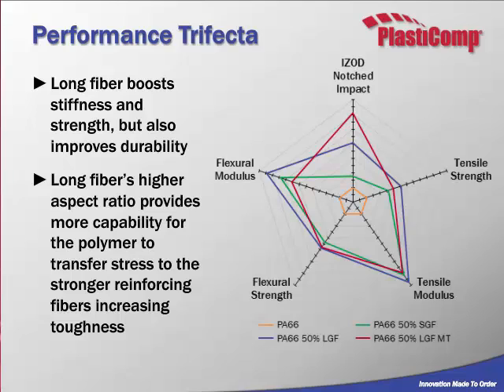Now this slide just shows a spider diagram of several materials that are compared to each other. In the center is the unfilled product, and you can see the properties there are quite low in comparison to even the short glass product, which is labeled as SGF. And then we have two products that we're highlighting here. The first is our standard long glass fiber product, and then we also have what's called a maximum toughness grade, which is the MT product. Where that really stands out is in its impact performance, and we'll touch on that a little bit later in the presentation. But you can see the nice balance of properties you get with the long fiber materials compared to short glass. This really spells that out.